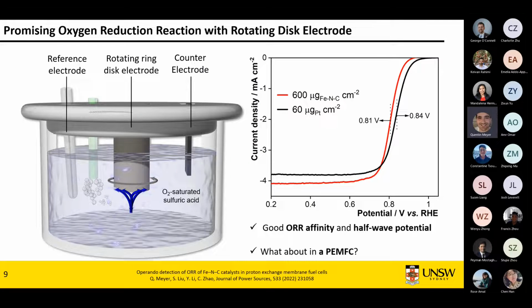Now, looking at the performance of our catalyst in RDE. In RDE, it's quite a good system. You've got your reference, your disk electrode, and your counter electrode. We get some pretty decent performance, a half-wave potential of 0.81 volt for iron and 0.84 for platinum. So this is a good start. That's typically when you go, okay, I'm quite happy with that, I can start going into a real device.